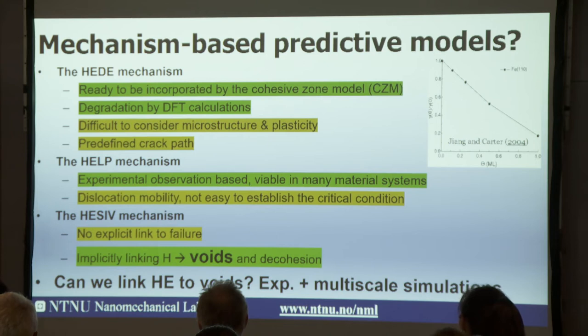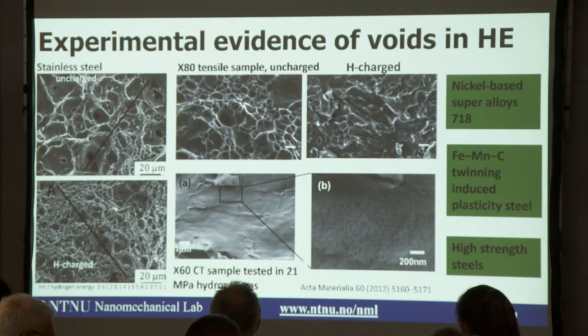The homework includes two parts. First, we want to look at the experimental evidence about the void in hydrogen embrittlement. Second, we want to use our multi-scale simulation to understand how the hydrogen will influence the void nucleation, void growth, and void coalescence. So these two parts I'm going to talk about. We have looked at the literature for the stainless steel. This figure shows an uncharged fracture surface. We have very nice dimples. However, if you look at the fracture surface with hydrogen, we still see the dimples, maybe in a different scale.